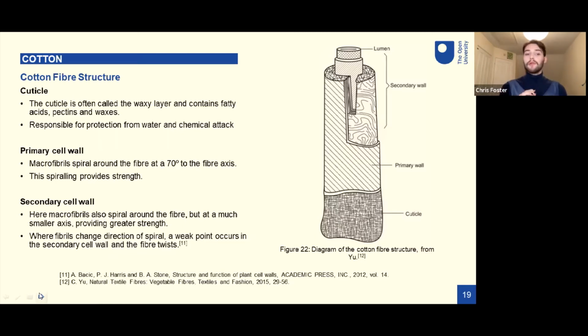If these macrofibrils change a direction of the spiral, so they're spiraling this way and then they change to that way, a weak point actually occurs in the cell wall, and the whole fibre, the twist of the fibre, will also change direction. And this will be seen in a minute as well. I should lastly just mention the lumen. The lumen is kind of a hollow structure that travels the length of the fibre, and this occurs from the way that the fibre grows.